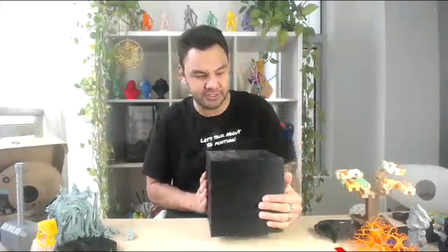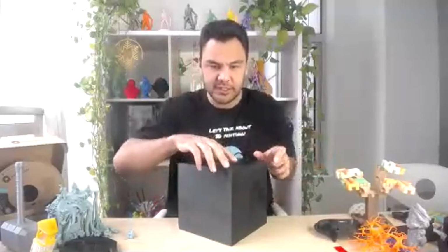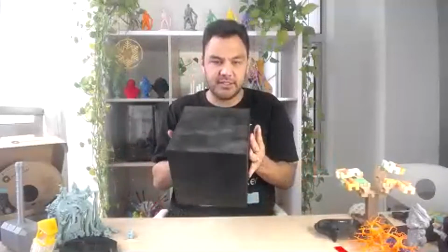So this was printed, I believe, on the Ultimaker 2 Extended Plus. So we printed this one with no heated chamber. The bed was at 45 degrees and we used a glue stick, and that was the result. So you can see there's no warping at all. I hope you can see well. You see, it's dead flat. It's very, very flat. So that's the best way to show warping.